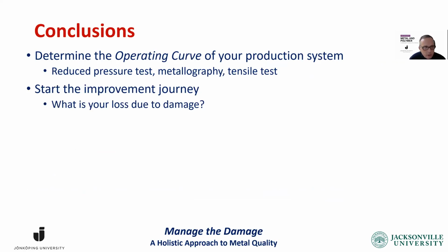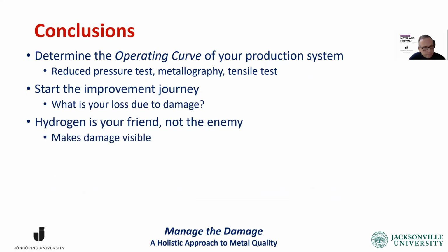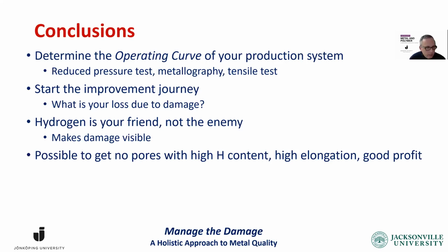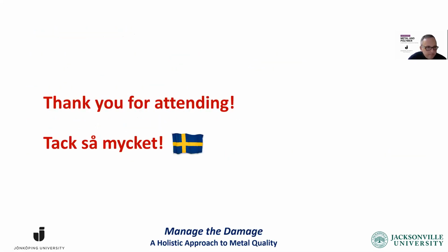What is your loss, entire loss due to damage? Hydrogen is your friend, not the enemy. It makes the damage visible. Stop sweeping the dirt under the rug. And it's possible to get no pores with high hydrogen content, high elongation, and make good profits.